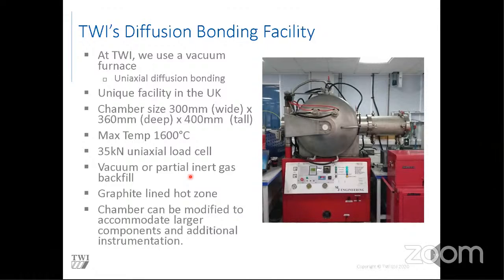There are certain situations, which I will discuss, where a partial pressure is beneficial. It's to do with something called vapor pressure of certain alloys - certain materials will vaporize at high vacuum. So the hot zone is graphite lined, and we can actually modify the chamber for larger parts if we need to.